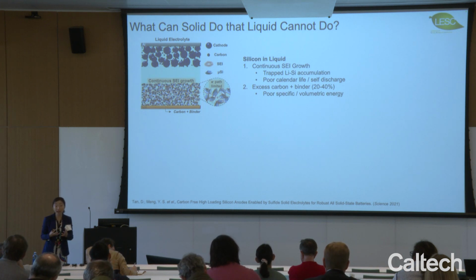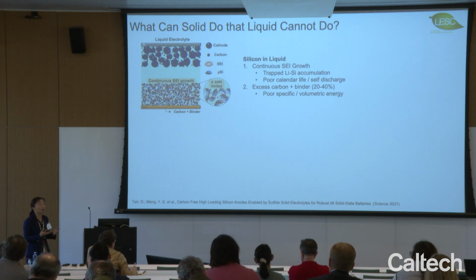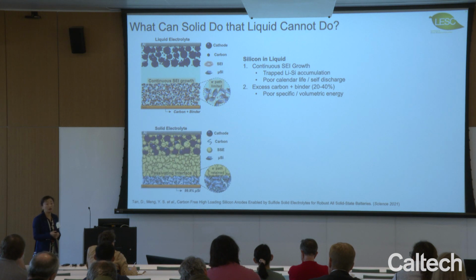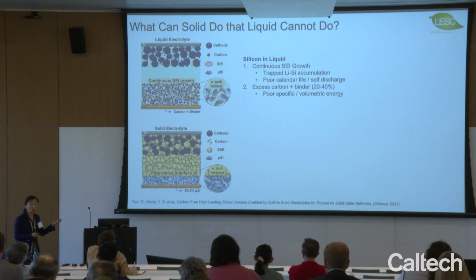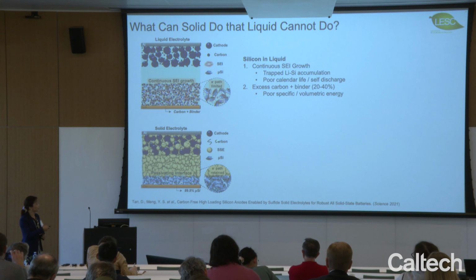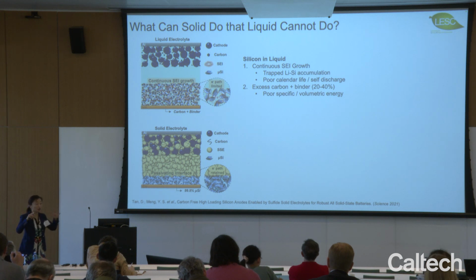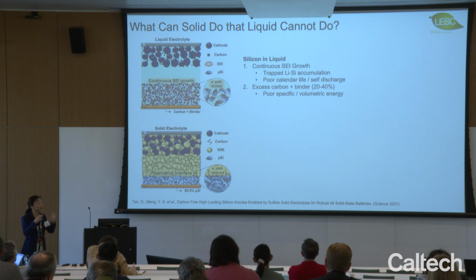So for almost 2 decades, silicon, even though a very promising anode material, could not make a significant impact in batteries. So let's think about what happened in the solid-state electrolyte. What we can do is that because the particle size can be precisely controlled, imagine your particle size for the solid electrolyte is relatively larger compared to the pores inside the silicon. And you just build a porous silicon anode, but without any of the carbon additives in it, okay?